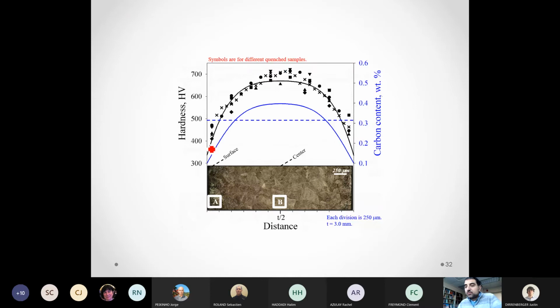What we next did was to decarburize this material. So we controlled the surface concentration of carbon to be around 0.15. We found through many trials that this was a good value. And we controlled the hardness, and then we can measure the hardness that results from this profile. So you could see at the center, the carbon content is still 0.4. But at the surface, as I mentioned, it's just above 0.1.